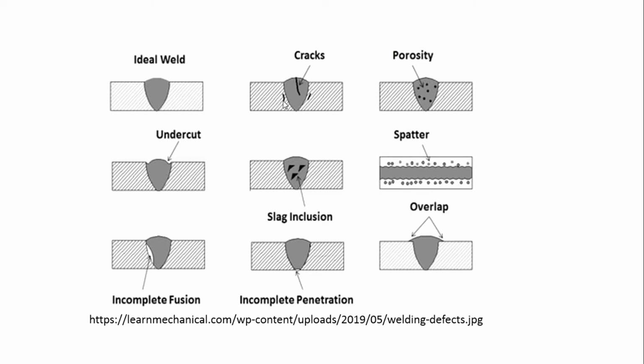If you are connecting Inconel materials, or using high carbon content materials, you will get cracks because of the formation of a hard phase of carbides. And you can see some porosity, which is nothing but gases that have been entrapped in the weld bead. If you carefully adjust the shielding gas flow rate, or sometimes reduce the speed of the welding process, any gas that is trapped or formed may try to escape from the weld pool. If your torch is moving very slowly, the melting time and the solidification time from liquid to solid will be longer, so there is a chance of the air escaping from the molten pool. So that's good.